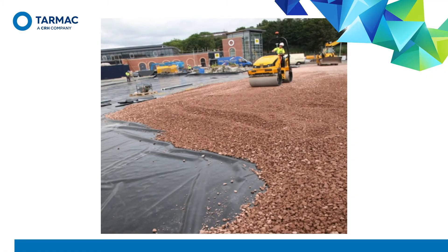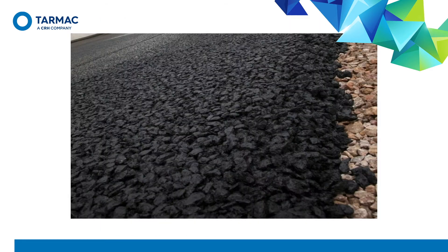On sites with really poor ground conditions — that's low single figure CBRs — it may be necessary for buildability, as much as anything else, to import some sort of ground improvement material to go in below the GRL. But any sort of crushed rock capping layer would generally be disregarded in terms of water storage capacity. The granular reservoir layer is a large, circa 40 mm, single-sized crushed rock, which typically delivers voids in the upper 30 or low 40 percents. It needs to be crushed rock to guarantee a degree of interlock which links directly to buildability. The asphalt layers are designed to live in a damp environment, but never actually sit in water — the water goes down into the GRL for storage — so durability is a key consideration in their design.